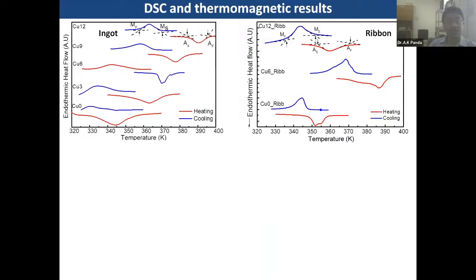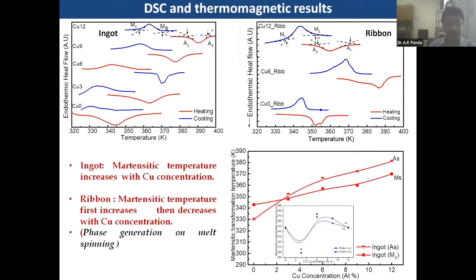These are simply the ingot and ribbon plots. You find that when we go from lower to higher copper content, you can shift the martensitic transformation towards the right, and that is how you can tailor the material. You can tailor the martensitic transformations, and therefore you can work with your magnetocaloric effect, because you are also able to change the magnetic transition temperature.